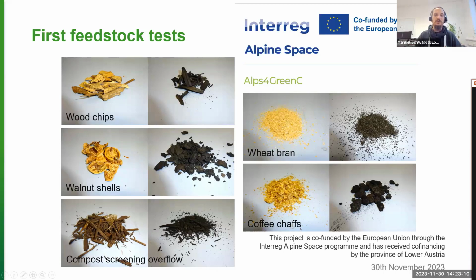Also very interesting was wheat bran, which we received from our local sugar producer. Very interesting was that wheat bran has a very low ash melting behavior. It is about 500 to 600 degrees C where the ash starts melting. And during our pyrolysis tests, we actually had quite some issues because it became sticky. So the biochar itself became sticky. And we estimate in the meantime that it is because of that really low ash melting behavior that it starts already at the edges of the biochar to sinter and therefore to connect with the next biochar particles.